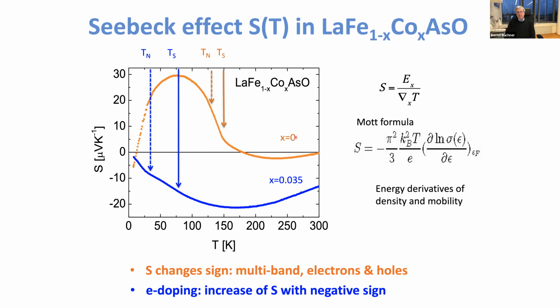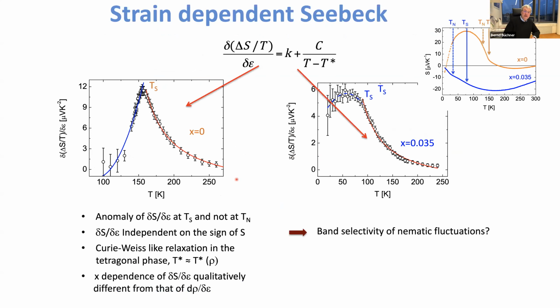So if you have the parent compound, equal to 0, so you have basically undoped compounds, holes and electrons with the same amount, therefore you have this crossing of the sign close to 0. If you electron dope the system, it becomes negative. So in both cases, we can now follow the strain dependence of these things. And the first message is it does not change when you change the sign of the Seebeck effect. So that simply means that the strain derivative is independent of the sign of S. And the easiest way to explain this is the band selectivity of nematic fluctuations. So apparently, only part of the Fermi surface, if you have these holes and electrons, really feels nematic fluctuations.